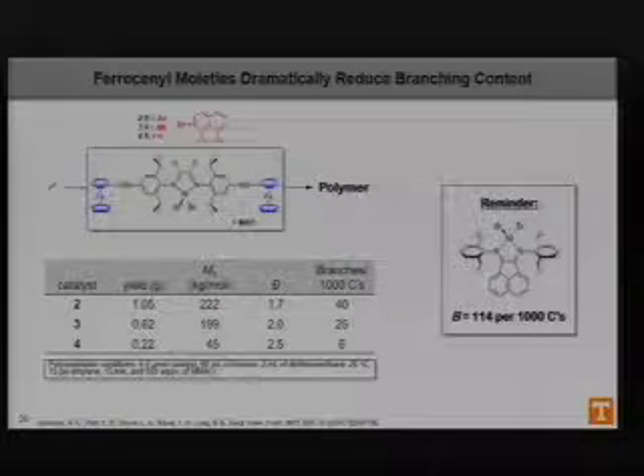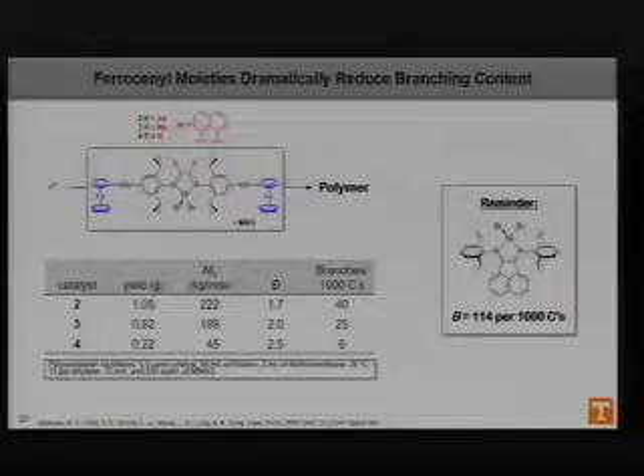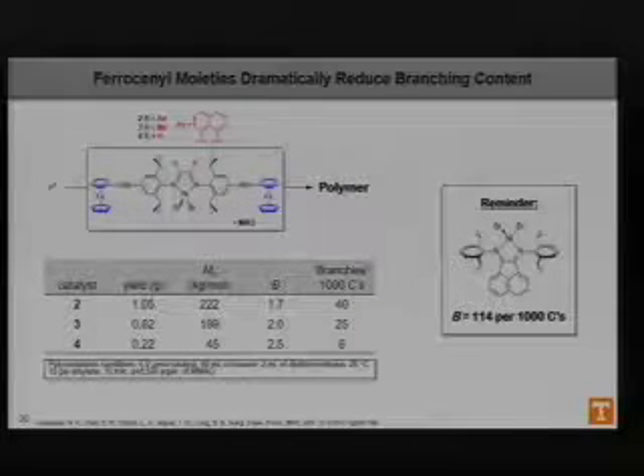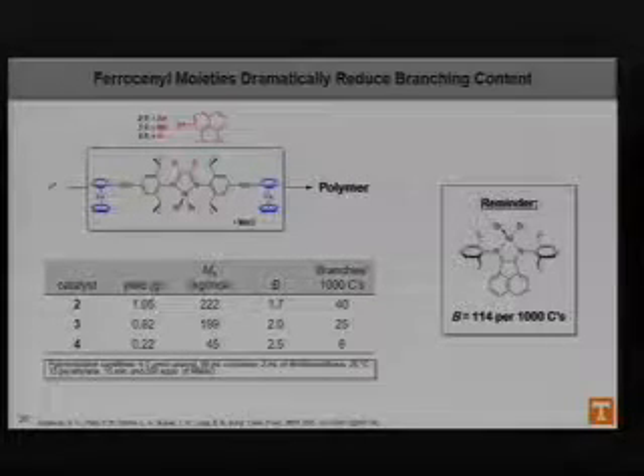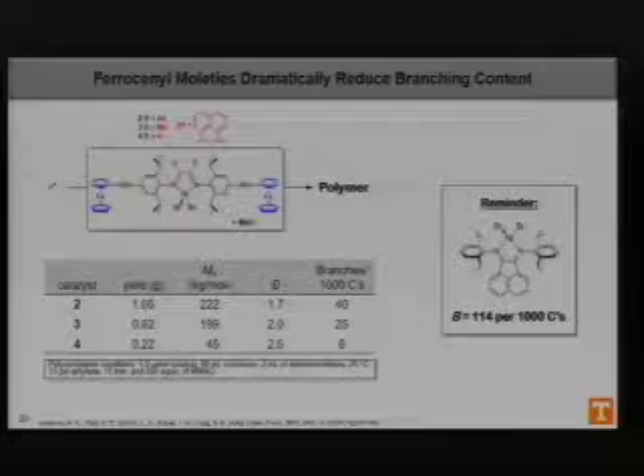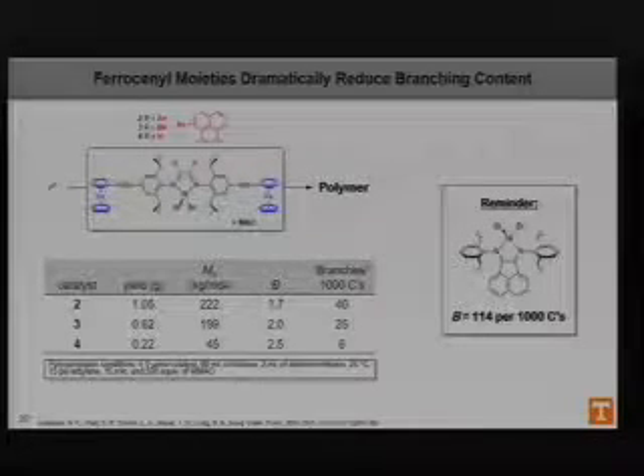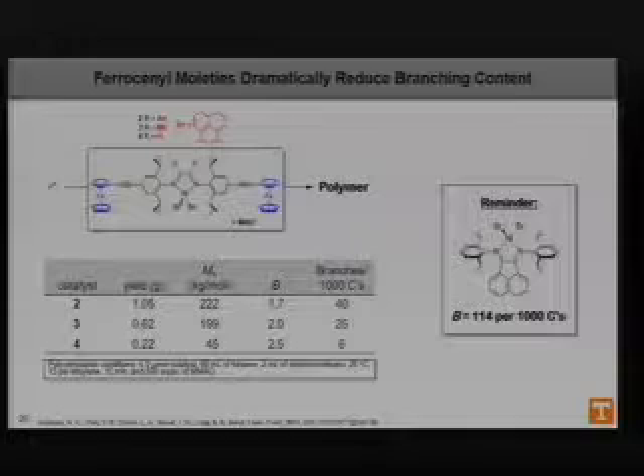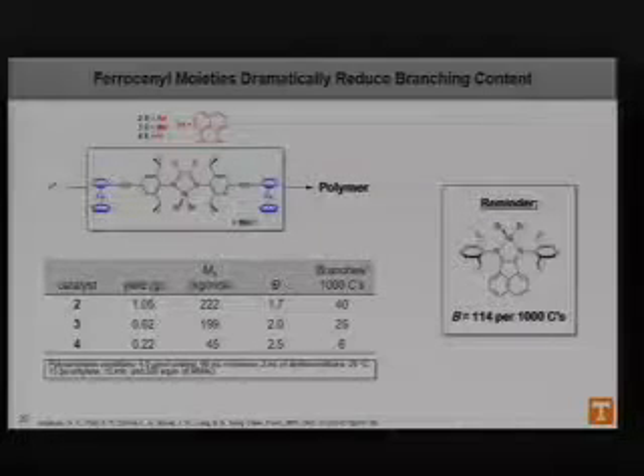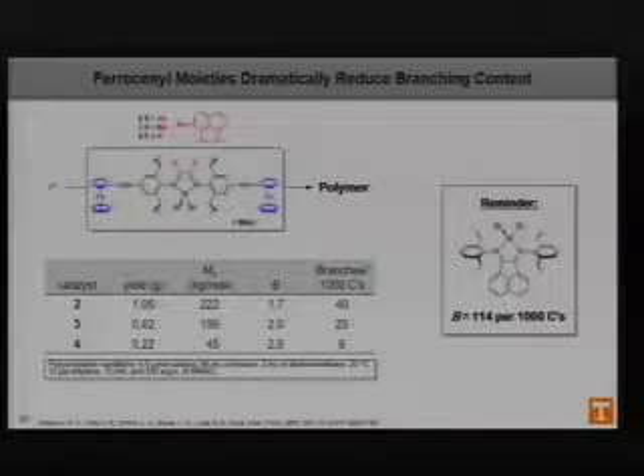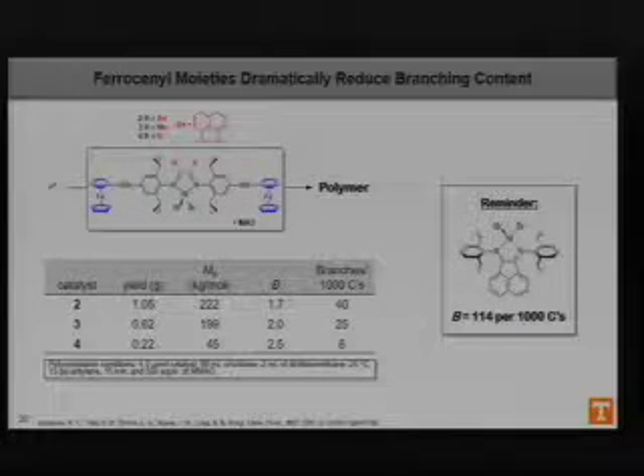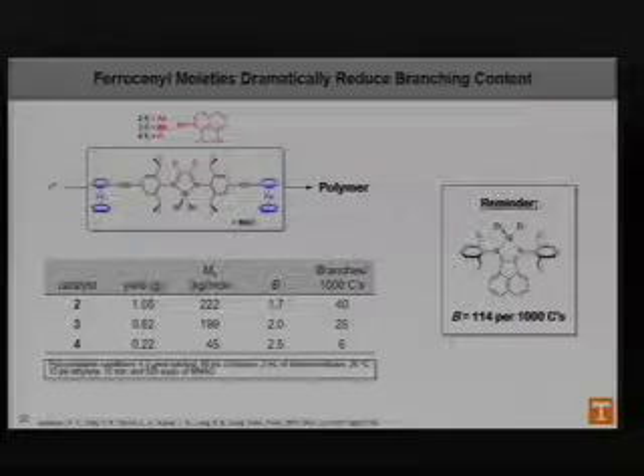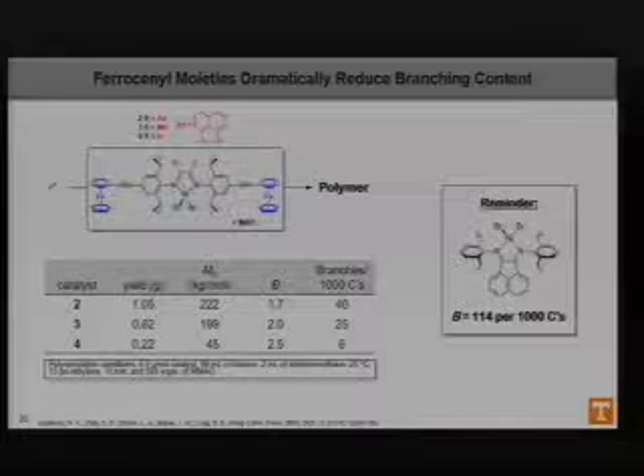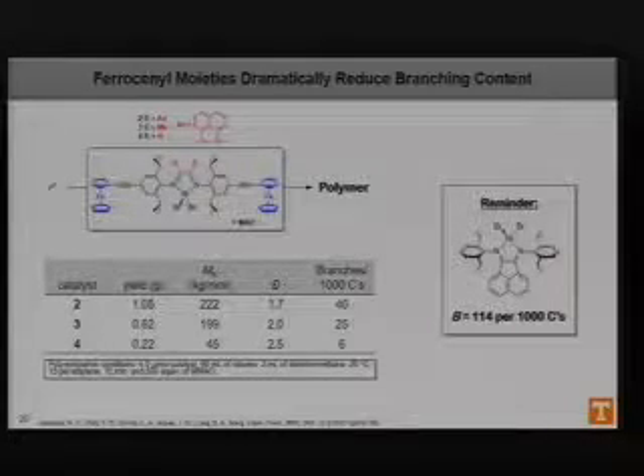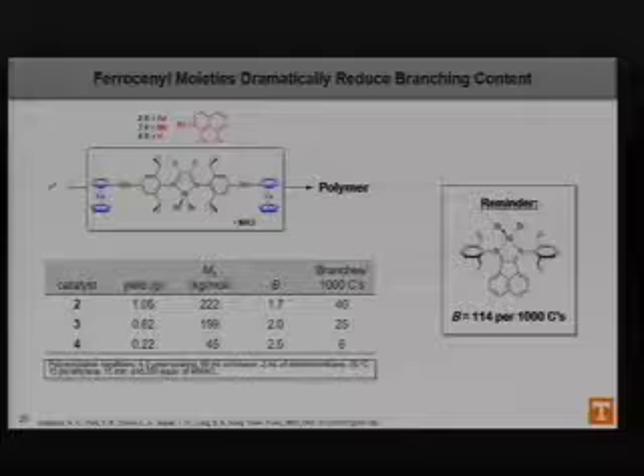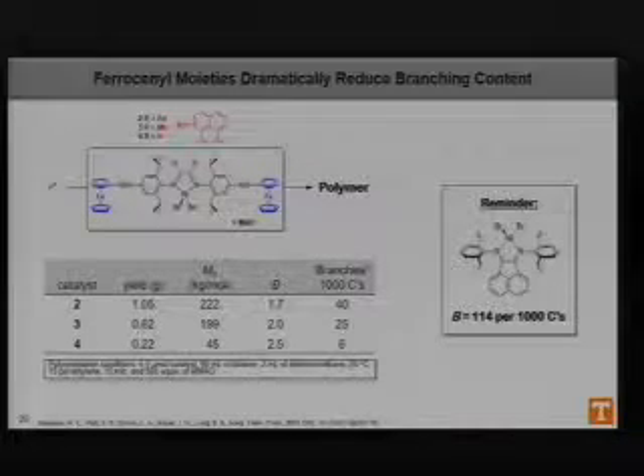So then we tried to do some preliminary polymerization results, and we found that regardless of catalyst 2, 3, or 4, and that's the acenaphthoquinone backbone, the methyl backbone, or just the hydrogen backbone, the yield was significantly decreased, as well as the branching went dramatically down, especially if you compare it to what Brookhart's catalyst was originally. That was 114 branches, all the way down to 40 for the exact same backbone with the ethynyl ferrocene moieties. So we did decrease the branching significantly like we had hoped we would.